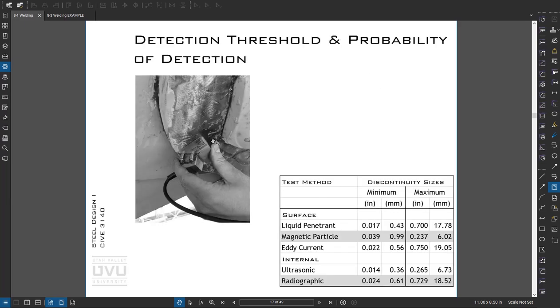All right, threshold of detection here is given, and it's important to understand this, that you can't find cracks under a certain size, and you can't find cracks over a certain size, but if you look at these 1/4 inch maximum size, those are very visible, so it tends to be realistic to find them. Although if you're looking inside, anything over a 1/4 inch, you're not going to be able to see with ultrasonic.